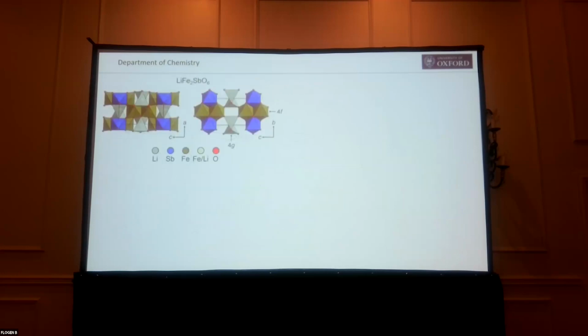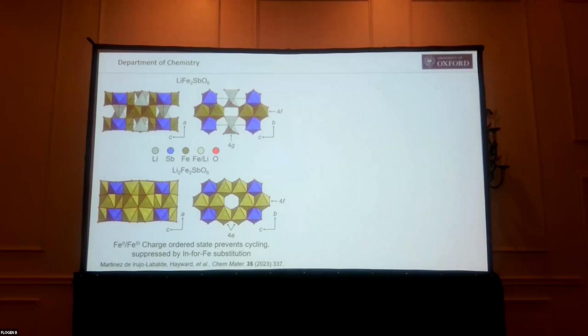Well, what we did was we took a view of stabilizing the lithium iron oxide system by using the post-transition metals, so things like antimony and tellurium. And what you find is if you introduce things like antimony and tellurium into the composition, they stabilize that framework. So here we have a layered material, not very layered, where each layer is of the same composition, but we have an ABAB stack of oxide ions, with the hexagonal structure, and then we have ordering of antimony and iron. Here's lithium. But as soon as we insert it into this system to make an iron 4+ compound, the iron jumps out of this site because now it's a lot bigger and it migrates to a different site. And we end up with this ordered structure.